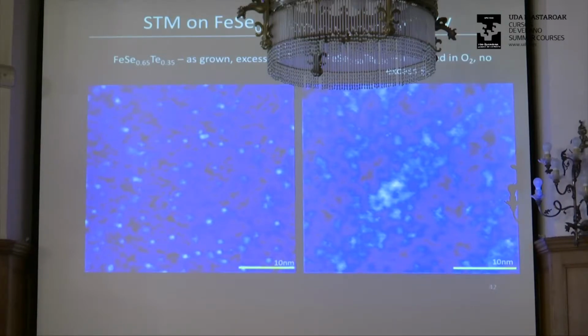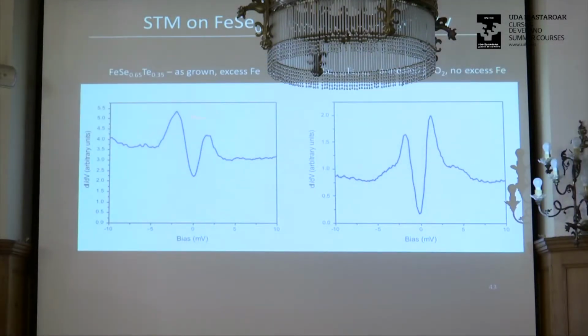And this is an S-wave superconductor, so this excess iron really destroys superconductivity. You can anneal these samples in oxygen and get rid of this excess iron, but it creates a lot of defects and impurities. So here's the superconducting gap. Here's 0. You can see it doesn't reach 0 on the sample with excess iron. And if you anneal it in oxygen, you can get rid of some of the excess iron, and still at 300 millikelvin, the gap still doesn't go to 0, okay?